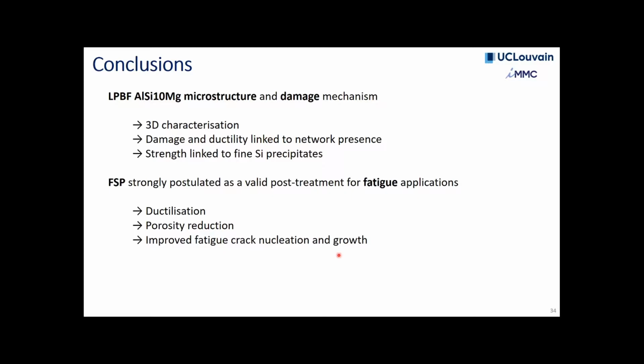It has shown a very significant reduction of the porosity, and this improves the fatigue crack nucleation and growth. And that's the most interesting aspect of the friction stir processing post-treatments, because the stress relief heat treatment that I've shown you as a comparison is interesting in terms of ductility, but not in terms of fatigue. So that closes my talk, and I'll be happy to take any questions.